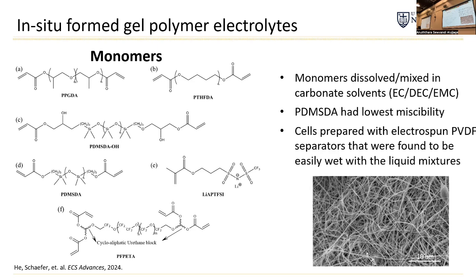With commercial separators, like Celgard, polyolefin separators, in a lot of cases we saw wetting issues. Once the solvent had these types of materials dissolved in it, it would sit on the surface of the separator as a drop, and it wouldn't easily wet it. So we knew there were some issues. We found that electrospun PVDF, which was made in my colleague's lab downstairs, the Young group lab, was easily wet with all of the liquid mixtures. So we used this PVDF electrospun mat as our separator material.